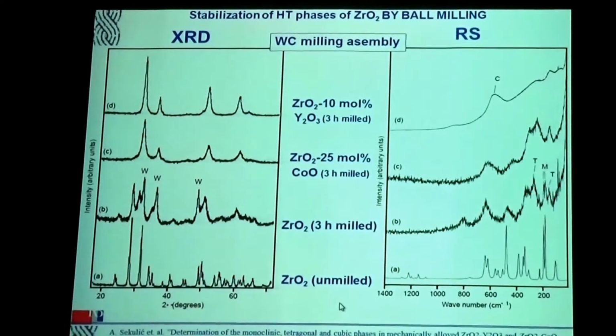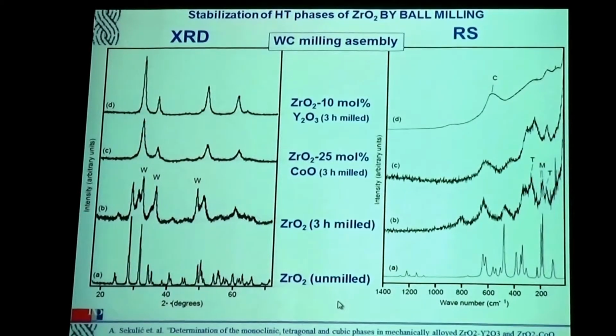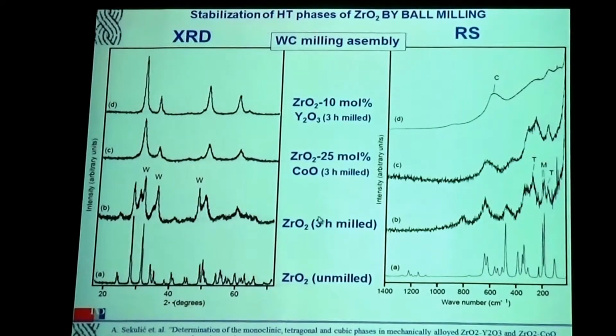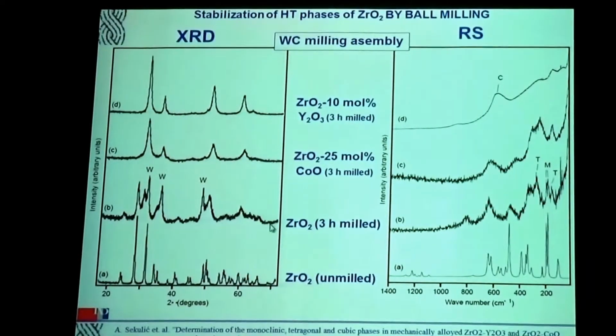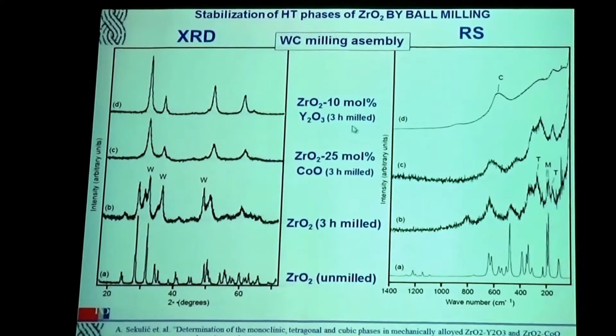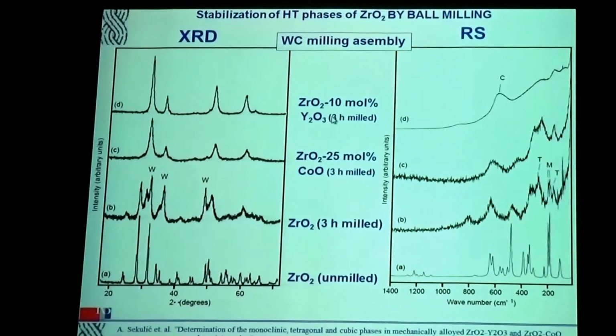So we prepared stabilized zirconia by high energy ball milling. We tried also to mill samples without any addition of other oxides for stabilizing, and we milled it with cobalt oxide and with yttrium oxide.